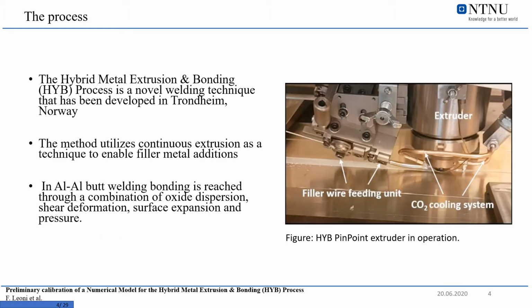As I said before, the hybrid metal extrusion and bonding process is a novel welding technique that has been developed in Trondheim, Norway. The method utilizes continuous extrusion as a technique to enable filler metal addition. In aluminum-aluminum butt welding, for example, the bonding is reached through a combination of oxide dispersion, shear deformation, surface expansion, and pressure. Here you can see a picture of the tool that is joining two plates of aluminum, and you can see the main parts of the tool.